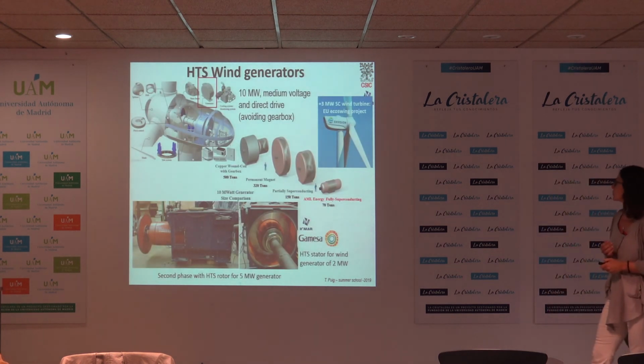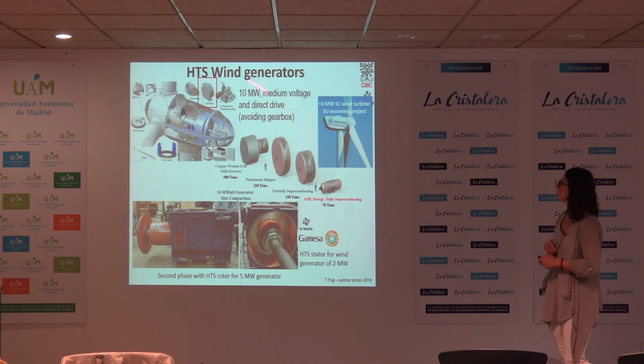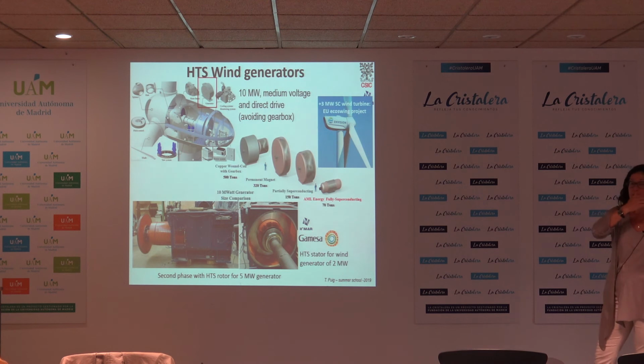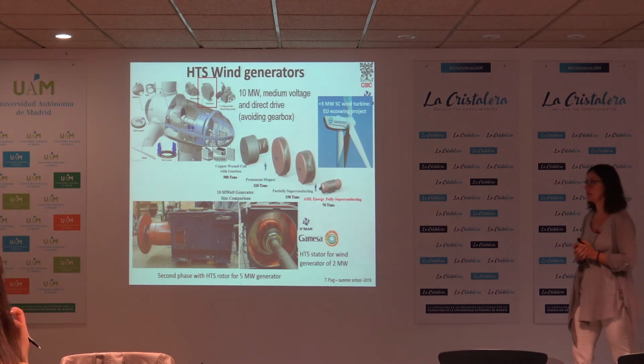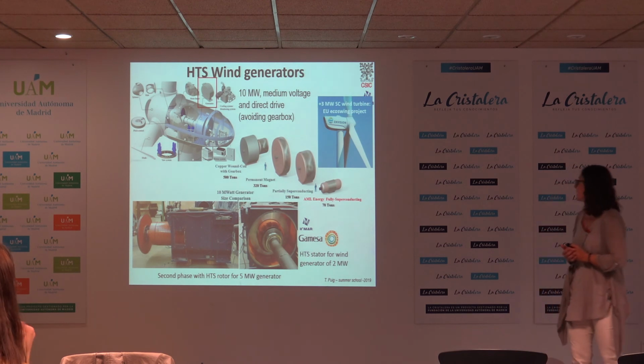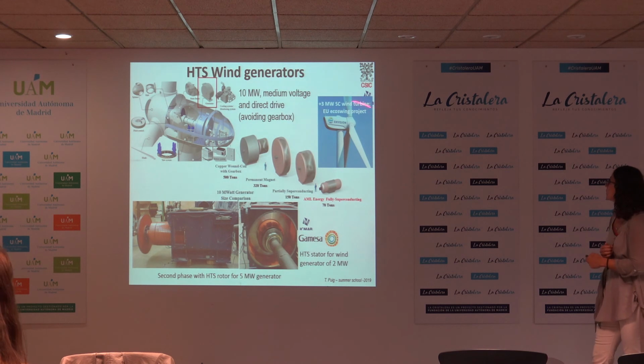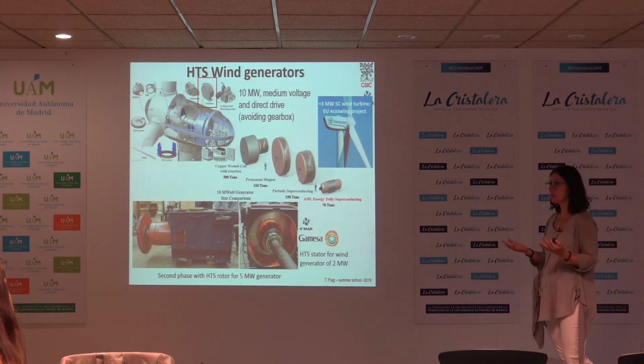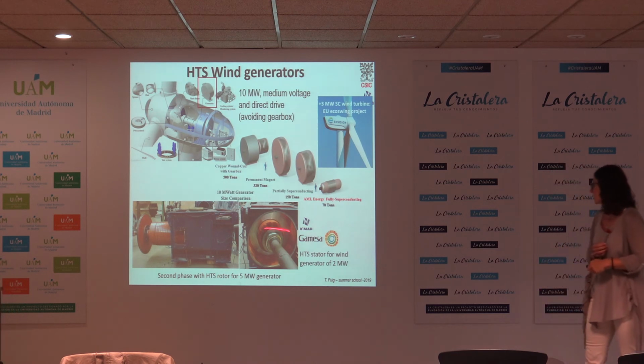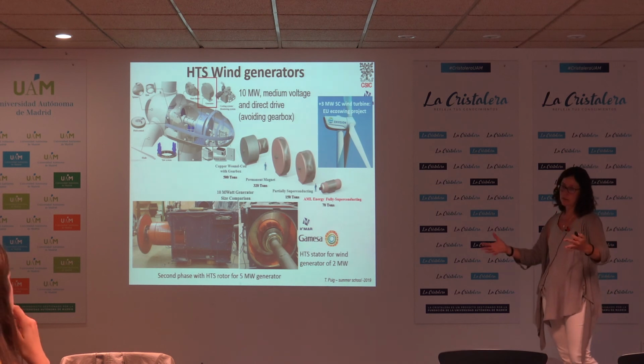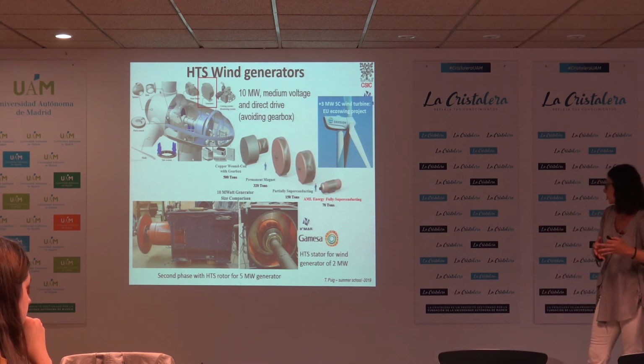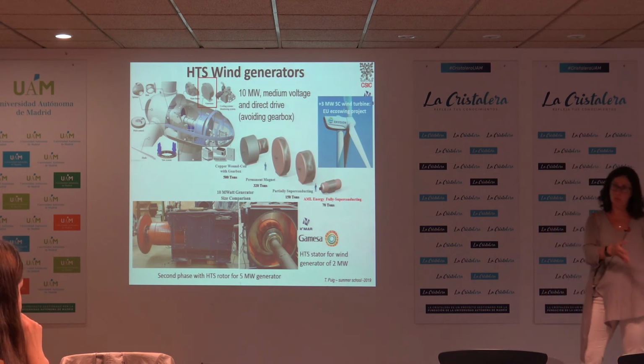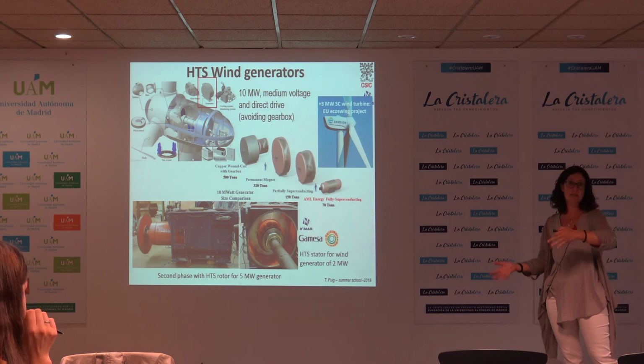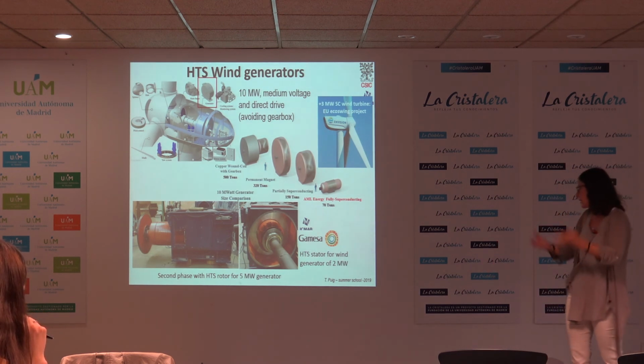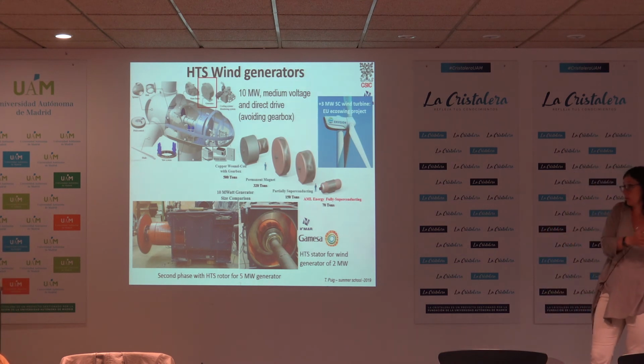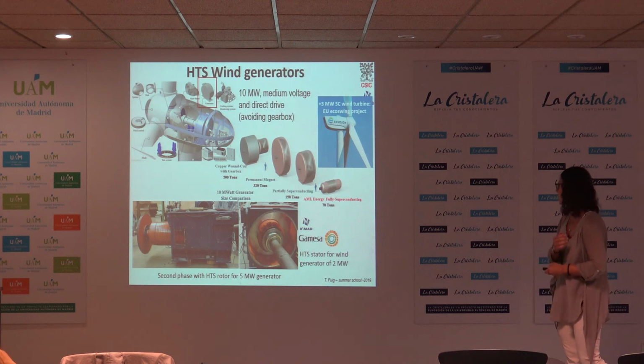In wind generators, that is also another possibility. In fact, when we want to go to 10 megawatts, it's a bit complicated with standard technology. Here you can see how much you can win in weight and in volume. There has also been a project in the EU demonstrating a 3 megawatt superconducting wind turbine. And we also worked with Gamesa to demonstrate that we can take one initial standard Gamesa generator of about 0.5 megawatts and transform it to 2 megawatts if we change the conventional stator to a superconducting stator. Now there's a second phase, which would be to change the rotor also to a superconducting rotor, and that would enable us to go to a 5 megawatt generator.